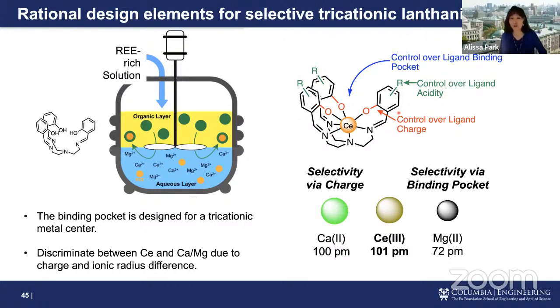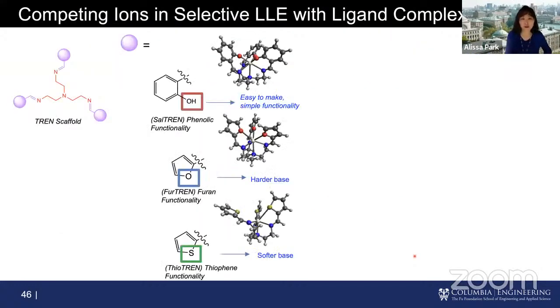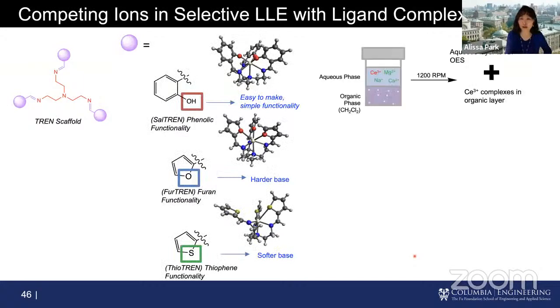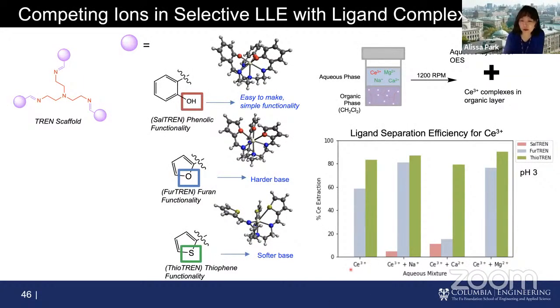So we really wanted to see competition between calcium and magnesium and cerium, for example. And here are some examples with different binding energies and data showing cerium versus sodium versus calcium versus magnesium. In all cases, we were able to selectively grab cerium in the presence of high concentrations of sodium, calcium, and magnesium.